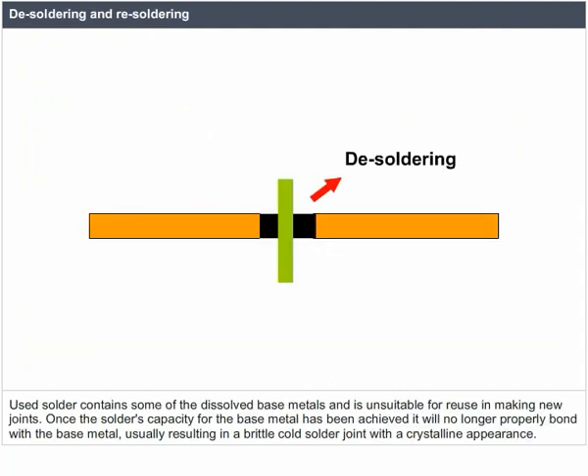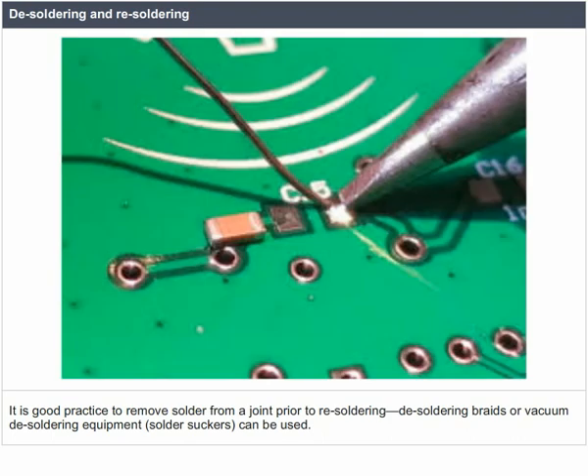Desoldering and resoldering. Used solder contains some of the dissolved base metals and is unsuitable for reuse in making new joints. Once the solder's capacity for the base metal has been achieved, it will no longer properly bond with the base metal, usually resulting in a brittle, cold solder joint with a crystalline appearance. It is good practice to remove solder from a joint prior to resoldering.